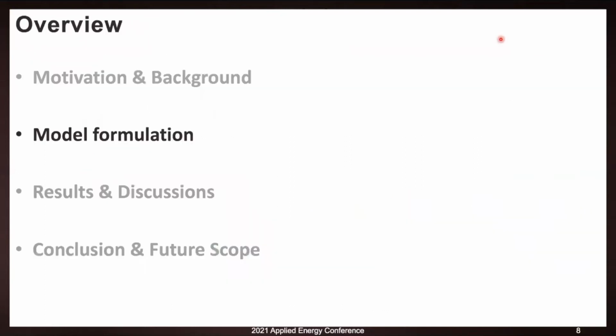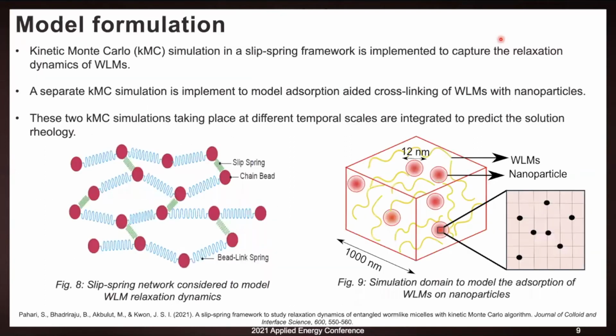these models. Coming to the model formulation section, to model the rheology of WLM-based VES fluids, a slip spring framework was considered in this study. In this framework, the WLM chains are modeled by beads which are connected with springs of harmonic potential. The entanglements between the WLMs are modeled via slip springs. These slip springs can slide past the WLM chains, which essentially mimic the dynamic nature of the entanglements present in